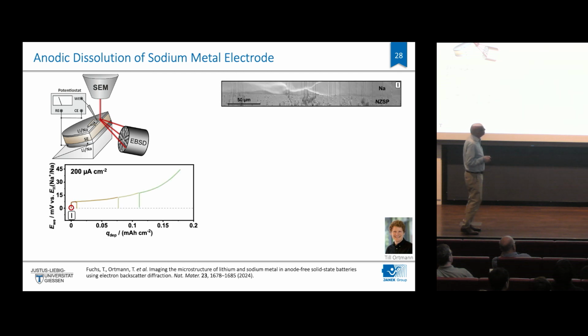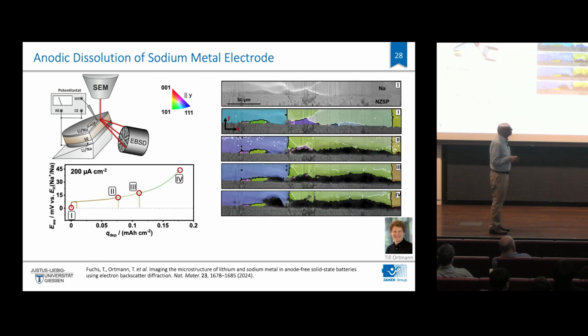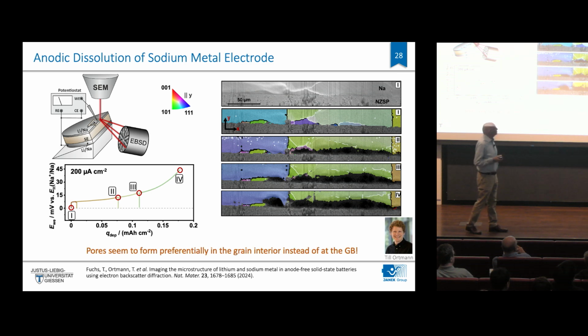And what you see here is, in the color code, the sodium metal upon stripping, how it develops. And you see here pores are being created, as we saw. A big pore is being created here, and we have very huge grains. And that was sort of the starting point for getting deeper into all that.